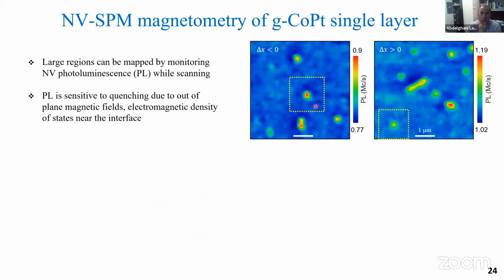So, for example, in here, we bring the NV to one of the substrates, negative gradient and positive. Now by scanning the tip across the sample, you can see isolated bubbles, for example, for negative and for positive. Also, you can see isolated bubbles or skyrmions, and certain worms. And usually this PL is sensitive to quenching. I can explain later why.